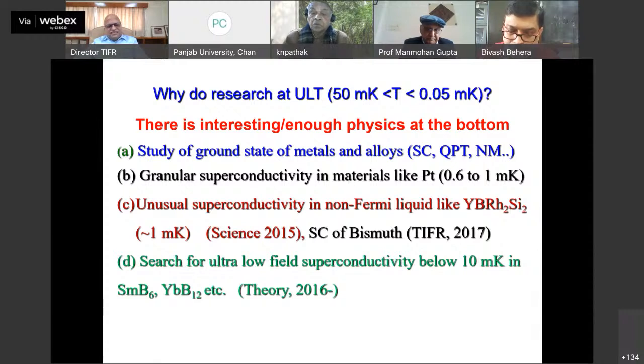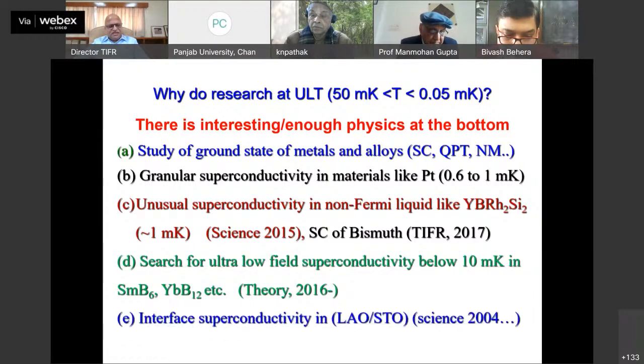There are also a lot of theories which seem to suggest some exotic materials like samarium boron 6 and ytterbium boron 12. All of them will show superconductivity, but the mechanism for superconductivity is completely different from the mechanism which we have known so far. Then the other interesting aspect is the two insulators, lanthanum aluminum oxide and strontium titanium oxide. You take these two layers and the interface starts superconducting. And so that is another unusual result for which you need temperatures down to at least 10 millikelvin to investigate.